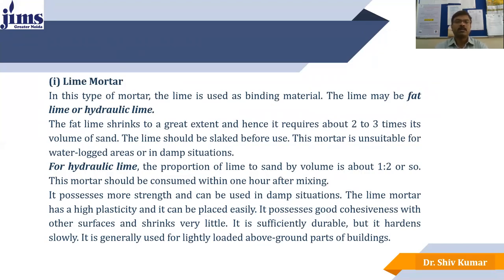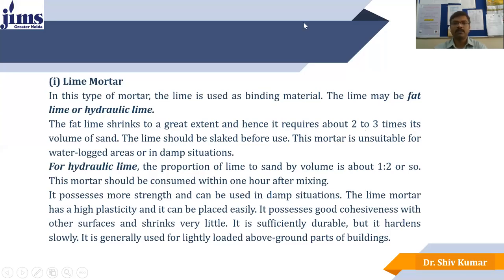In lime mortar, lime is used as a binding material. We use either fat lime or hydraulic lime. Fat lime shrinks greatly and requires mixing two to three times its volume of sand. It should be slaked before use and is unsuitable for waterlogged areas or damp situations; it should not be used for foundations or wells. For hydraulic lime, the proportion of lime to sand by volume is 1:2, and this mortar must be consumed within one hour after mixing as it hardens rapidly.